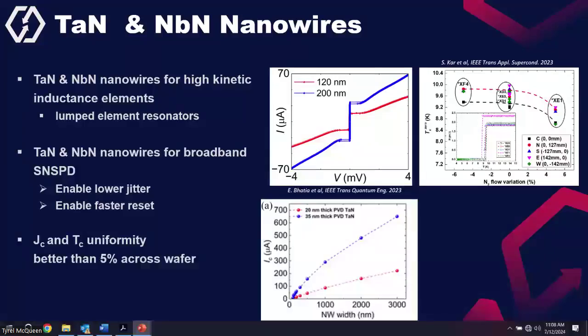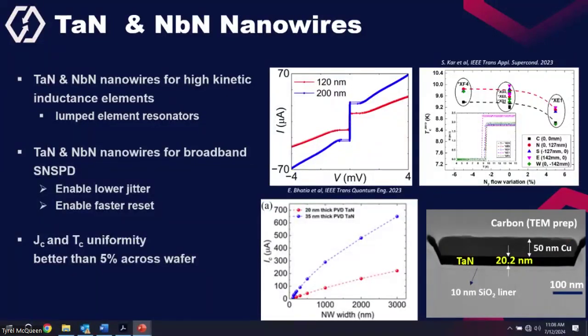And so we have talked about resonators, capacitors. For lumped element resonators, we need a capacitor and then we need an inductor. And we plan to use a nanowire as a kinetic inductor, as the source of that inductance. So for that, we fabricated Damascene nanowires. As you can see here, this is a tantalum nitride Damascene nanowire. And the advantage of using this scheme is that we can fill it with anything, either a dielectric or any other material. We chose copper here, which acts like a heat sink.